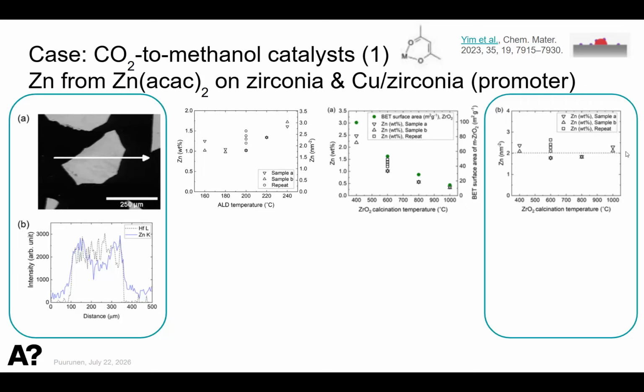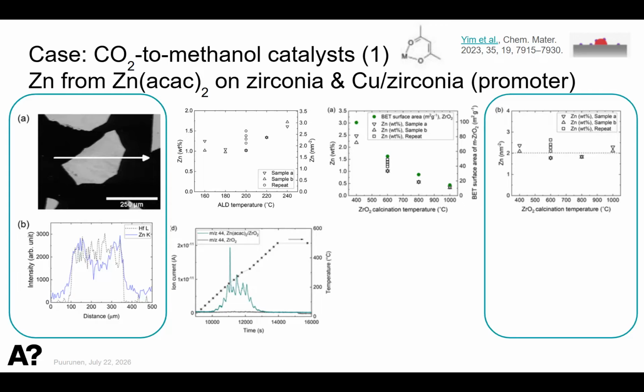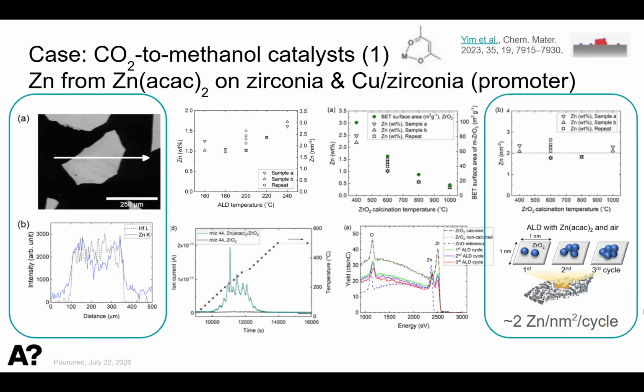So it probably means that it's steric effects that are limiting the amount of zinc there, and not that we would be running out of reactive sites. Then we made a test where we were heating the sample in, I think, synthetic air, and we found that once we are at 400 and beyond, we don't get any more oxidation products. So we made 3 cycles, and we again got roughly 2 per square nanometer per cycle. From low energy ion scattering, we could see that after the first cycle, basically all the zinc atoms covered the zirconia. So we could probably say that we had single atoms, although we don't know if they were next to each other, but they were at least not on top of each other. But in the further cycles, we didn't cover so much anymore, so probably we then had more like zinc oxide particles.